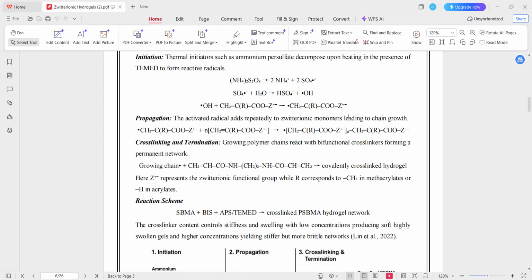The final stage is cross-linking and termination. Here, bifunctional cross-linkers such as methylene bisacrylamide react with two different polymer chains, forming covalent bridges between them. This converts the linear polymer chains into a permanent three-dimensional hydrogel network. Termination occurs when two radical chains combine or when a radical reacts with an inhibitor. The amount of cross-linker used plays an important role. If a low amount of cross-linker is used, it produces soft and highly swollen hydrogels, while higher concentrations produce stiff but more brittle networks.